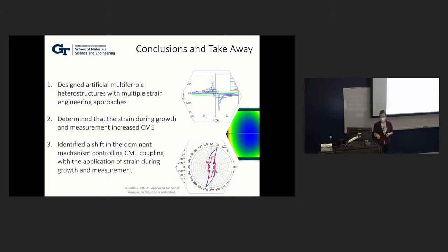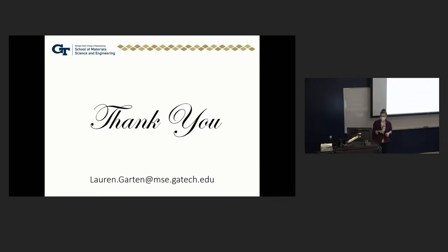So with that, I'll say that we have designed these artificial multiferroic heterostructures. We use multiple different strain engineering approaches. We found that for films grown with strain and measured with strain, we had this increased converse magnetoelectric effect, and identified this shift that's occurring in the mechanisms that led to this, which we need to dig into deeper. So with that, I will say thank you and leave my email up here if you have any questions.